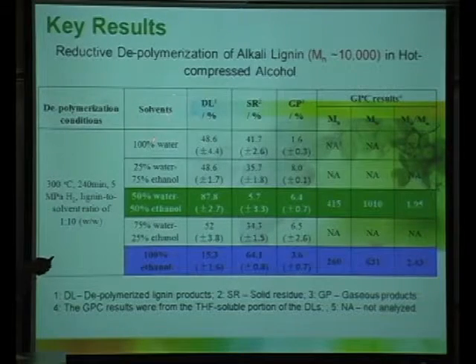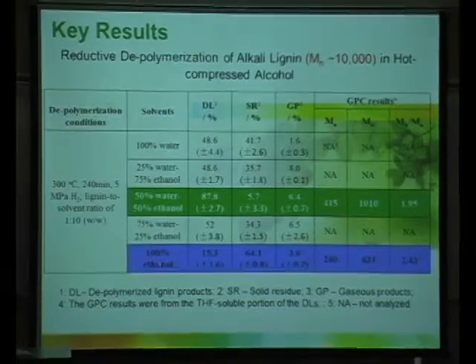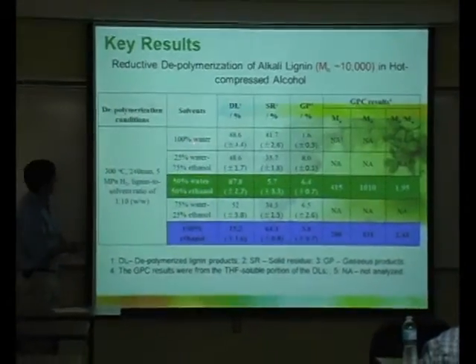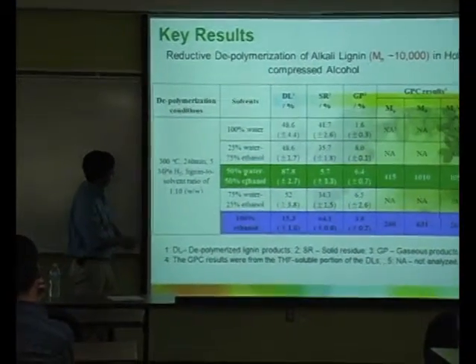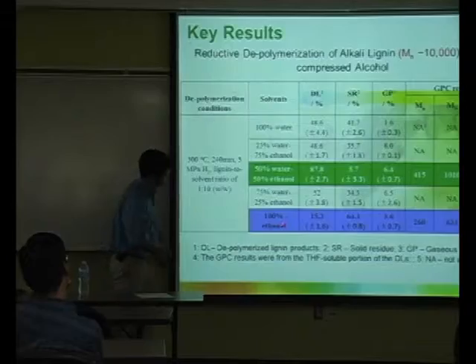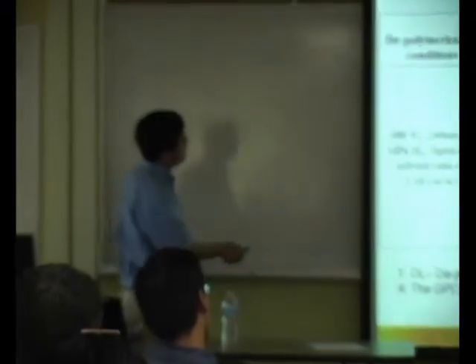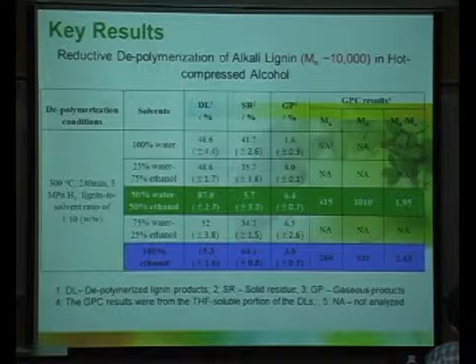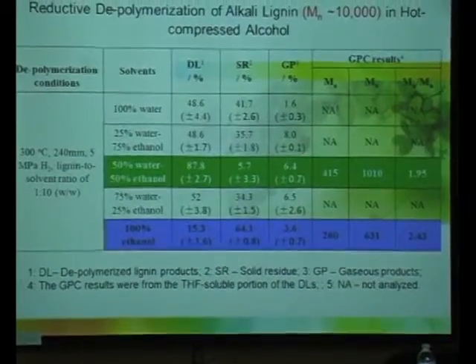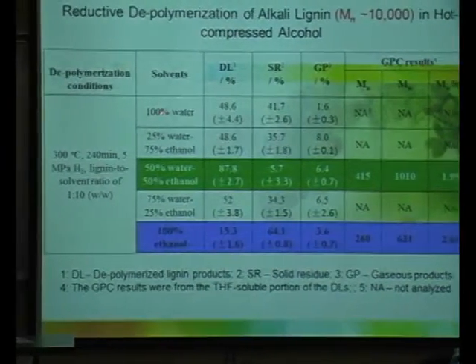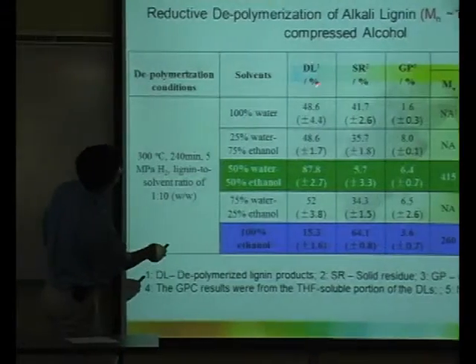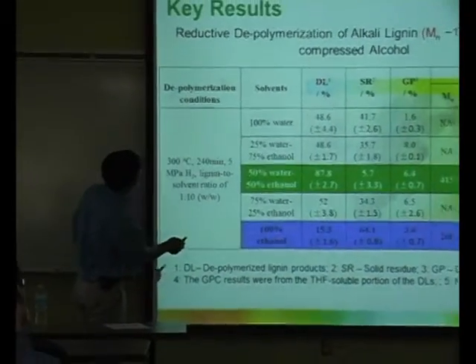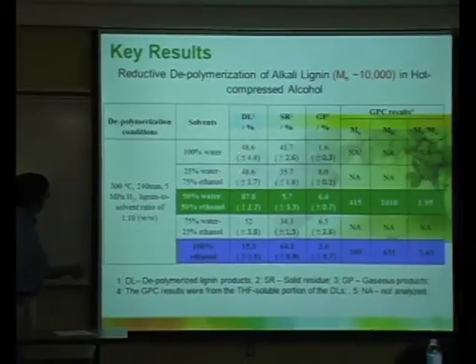And then we can depolymerize this lignin in different solvent systems, including a water-ethanol mixture, and including 100% ethanol. So we compare the different solvent systems, and we can see the performance. In the water system, it's very simple. Just water as the solvent, it's a green solvent, because water is not any environmental issue. And we can get a depolymerized lignin, about a 50% yield.